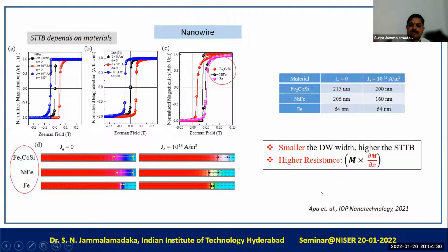As we have high resistance for the domain wall, the more and more spin transfer torque bias can be observed in the system. But on the other hand, if you look at the permalloy, the domain wall width is between Fe2CoSi and iron. So that is the reason why we do see a moderate spin transfer torque bias in the permalloy.